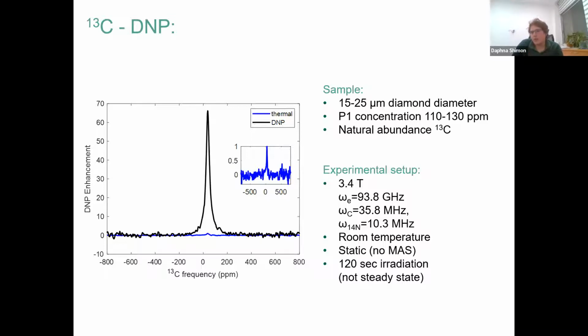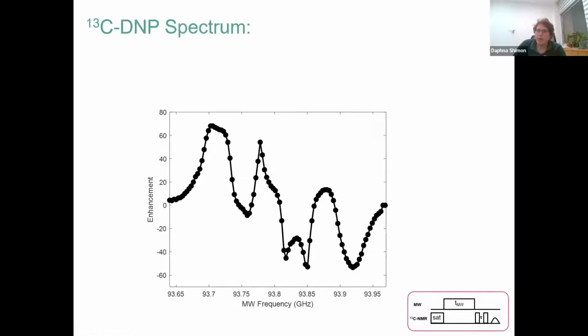The setup is pretty easy to build for yourself, and because of the long relaxation time, I only worked at 120 seconds or about 300 seconds and not much longer than that. So, of course, in DNP, the first thing that I do after checking the enhancement, or even before that, is measure the DNP spectrum, which is the DNP enhancement as a function of the microwave irradiation frequency.